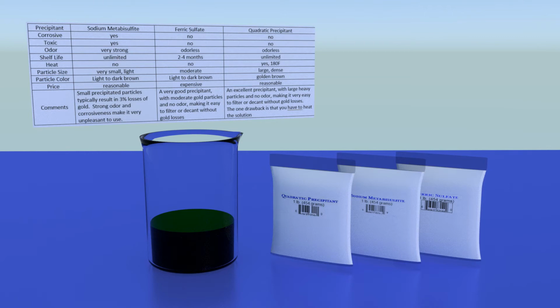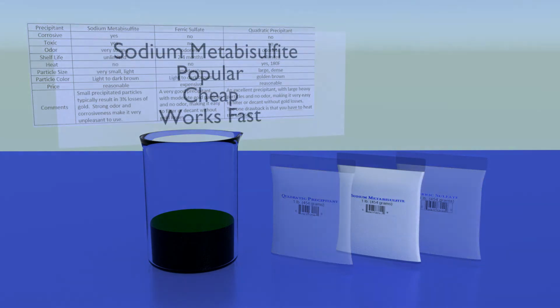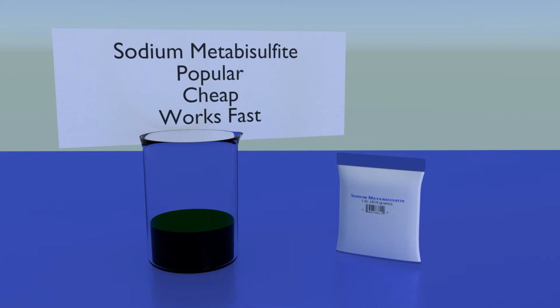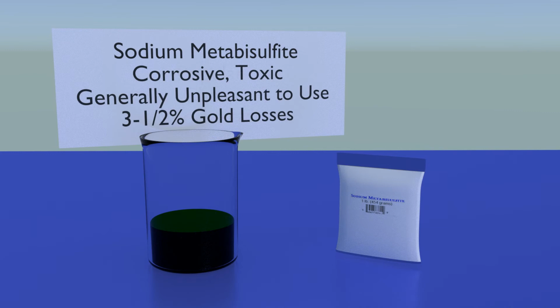Precipitating gold. There are several different selective precipitants available. If used correctly, all will precipitate gold with a purity of at least 99.95%. Sodium metabisulfite. Sodium metabisulfite is the most commonly used precipitant. It's inexpensive, and works quickly. On the negative side, it's corrosive, toxic, and generally very unpleasant to use. It precipitates very tiny particles of gold, some nano in size. Consequently, some of those gold particles, about 3.5%, pass through filter paper, and are lost.